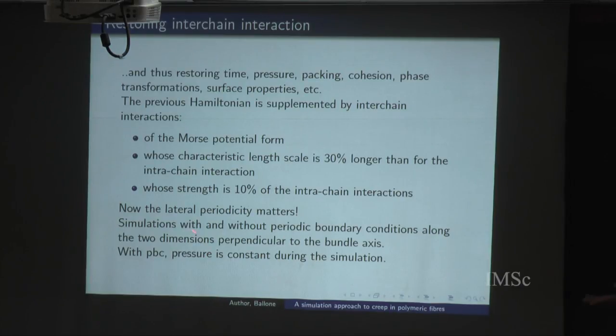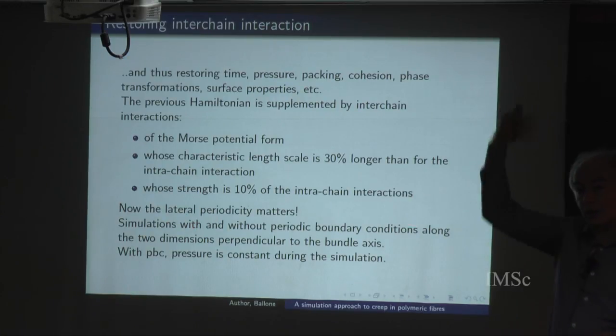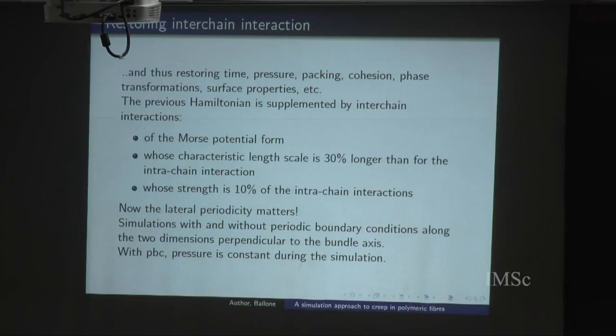And so for this reason, we did simulations with and without periodic boundary conditions along the two complementary directions. When we did have periodic boundary conditions, we set the periodicity. We used a Parrinello-Rahman approach to keep the pressure constant. And so we carried out our simulation.